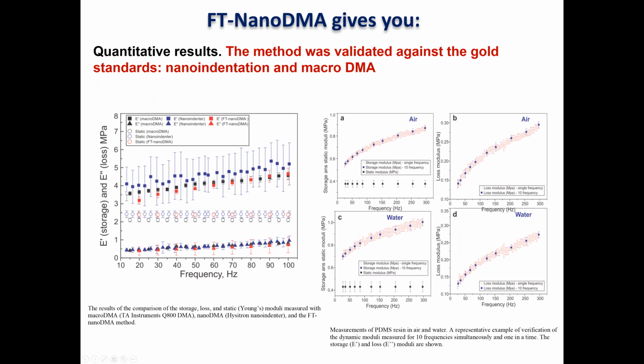For example, we did a comparison of our technique with other methods, for example, macro-DMA. This is a piece of very homogeneous PDMS elastomer, which was measured with macro-DMA, nanoindenter, and our technique. And actually, our technique matches macro-DMA very well, like big macroscopic measurements. With the nanoindenter, we have a fairly good loss modulus and static modulus, but for storage modulus, again, we have good agreement with macro, but the nanoindenter is showing higher values. And actually, we have an explanation for that, because again, it's a sort of nonlinearity we observe. We use a Berkovich probe, and you need to develop a pretty large area of contact before you get a linear regime.